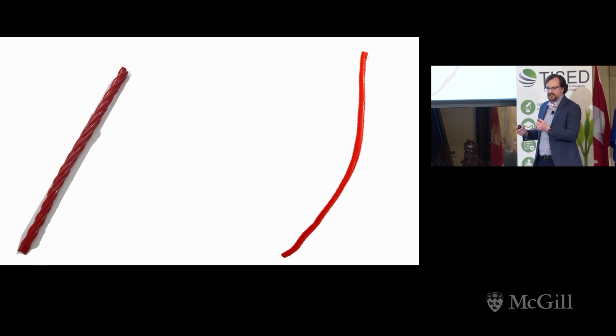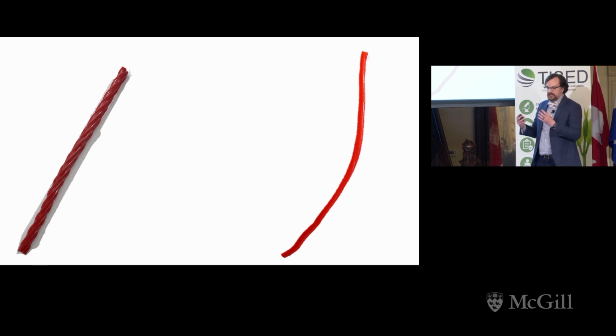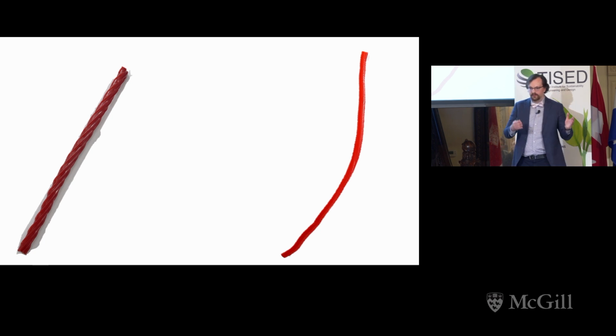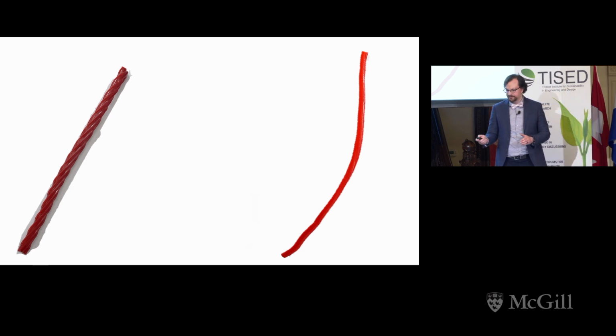You can see that there's a certain roughness to the surface and there's some grooves. The surface roughness does two things. It helps anchor the nickel particles better on the surface so they're more stable. And secondly, it's the surface roughness the CO2 can potentially react with, for the support material of the boron nitride nanotubes to assist with the CO2 methanation reaction.